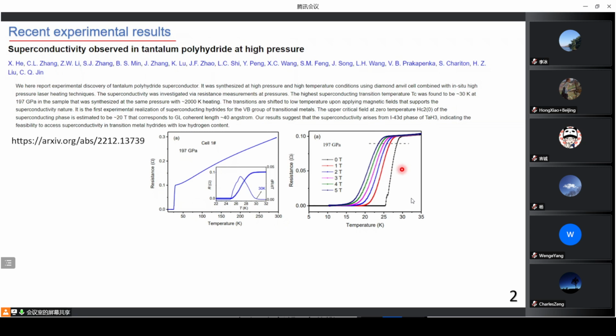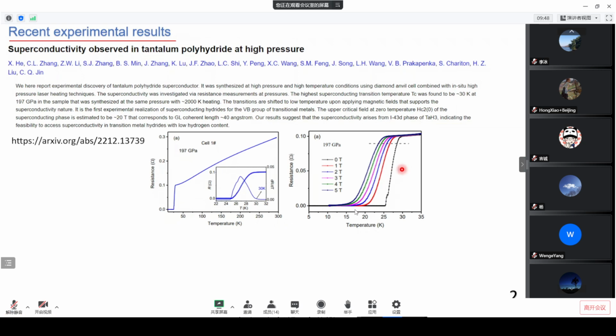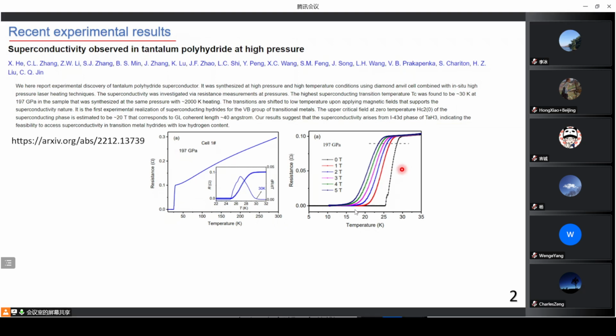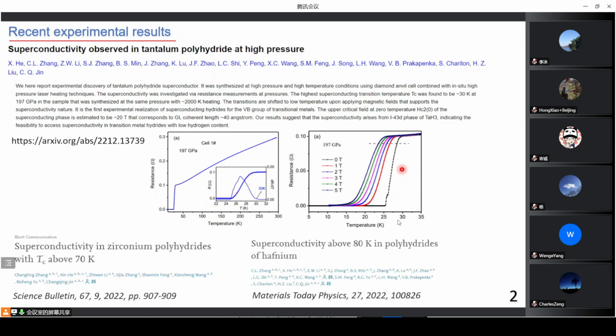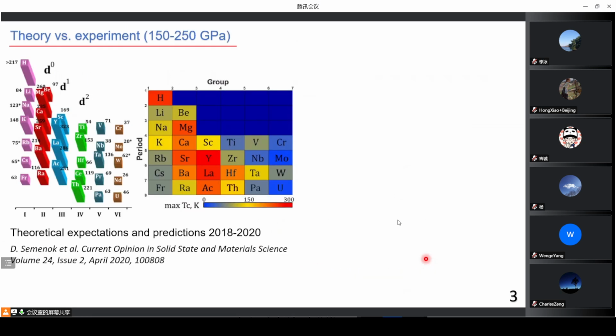I would like just to remind that for the tantalum-hydrogen system, it was predicted that at 200 GPa several other phases should form, such as TaH4, TaH5, TaH6, and they all should have much higher critical temperatures than was found in this experiment. The same group recently studied zirconium polyhydrides and found that TC of zirconium polyhydrides is just a little bit above 70 kelvins, and they studied hafnium hydrides as well and found that TC of those hafnium hydrides is also close to 80 kelvins.